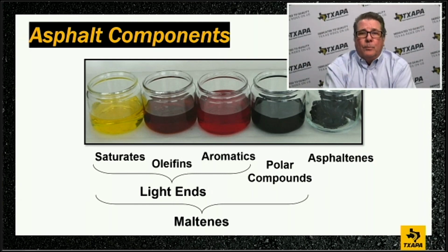When we start making actual asphalt and we're dealing with temperatures, the higher the temperature, the more we burn off these light ends. We've all heard the terminology, "Oh, they burned that asphalt up. I could smell it." Well, that's exactly what's happening. You're taking the light ends out, and all you're dealing with now is the asphaltenes, which is the very bottom of the barrel, and we don't want that. We want the components all to be together to be able to act properly. And that's what it's all about.